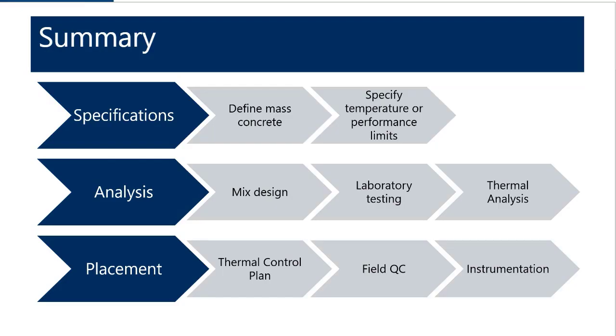So in summary, for mass concrete, the primary concern is temperature of the concrete element. The two things that we're primarily concerned with are the temperature differentials between the core and the surface layer contributing to thermal cracking, and second, high internal concrete temperatures can later lead to delayed ettringite formation, which would cause some expansion and cracking of the concrete element.